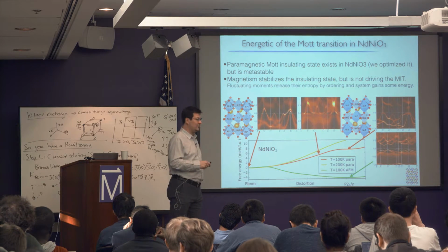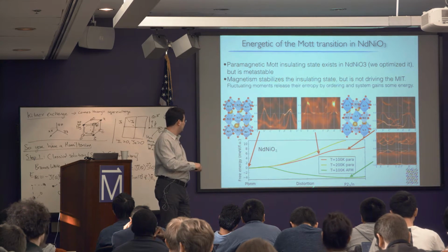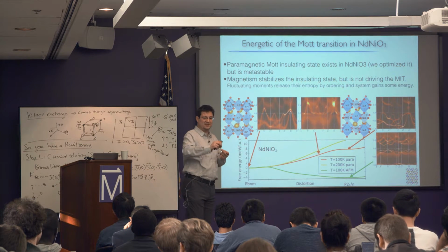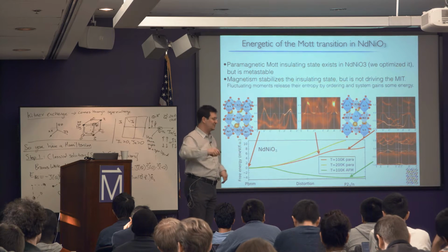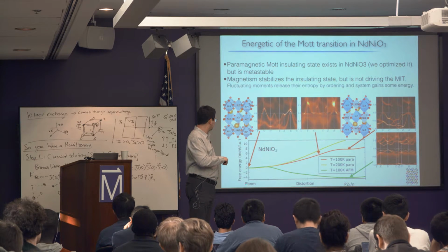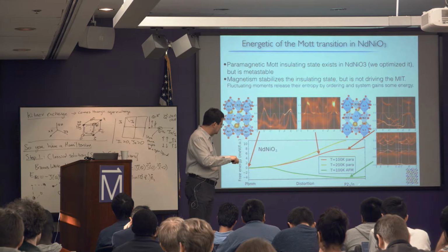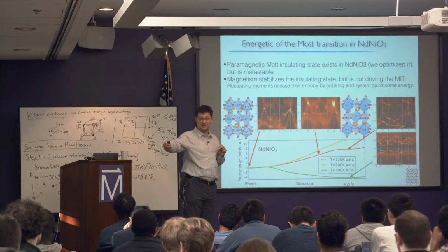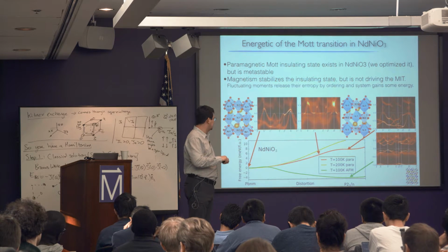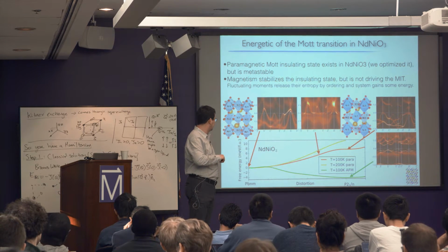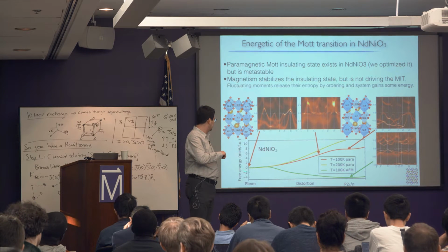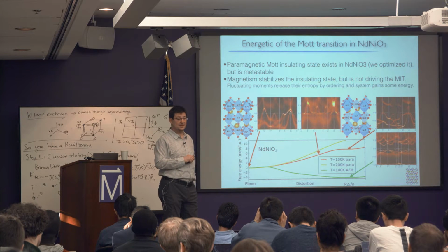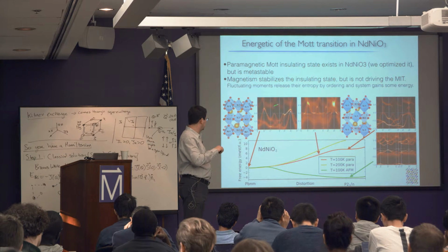And now if you can predict all 3 structures with the same functional, then you can draw a single line as a function of distortion. You linearly interpolate from the undistorted structure to the fully distorted structure, and you look at the free energy as a function of the distortion index. Then you can see that at high enough temperature, let's say 200 Kelvin, you have just a single minimum, and this minimum is the high temperature metallic state. It has a spectrum like that.